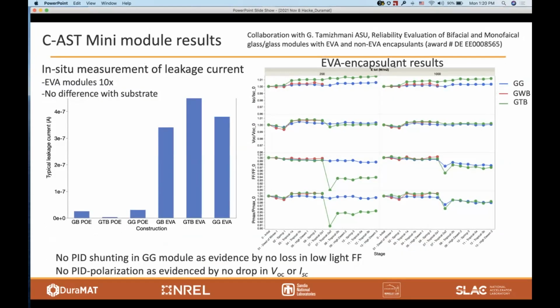Another thing we did with these mini modules, comparing the EVA and the different substrates, is look at the leakage current and look for degradation by PID shunting or PID polarization. So not too unexpectedly, the polyolefin encapsulant type backsheets show less leakage current, about an order of magnitude less than those with the EVA. In this particular experiment, we didn't see a great deal of systematic difference in leakage current between the different substrates, whether it be glass, transparent backsheet, or I think I made a mistake here, but a white backsheet. Just notice that. So no special difference in a substrate, but a great deal of differences associated with the encapsulant.